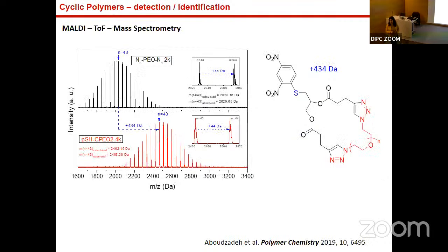MALDI-TOF mass spectrometry. This is a mass spectrometry that measures the mass of a single chain, for n times the monomer. So we have one line. The next line is n plus one, like this. This is an example from Ali's work, where we have the polyethylene glycol connected with this linker. This linker has a mass of 434 Dalton. And when we compare the linear precursor and the cyclic polymer, we observe the shift by exactly the mass of the linker that we put in this cyclic. So this is another way to identify the cyclic polymer.